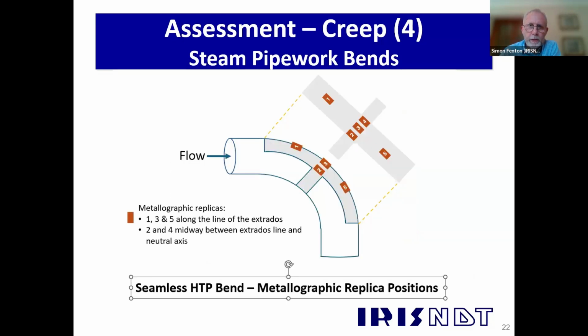Okay, next slide, please. So this shows the typical replication pattern for a bend on a main steam pipe or a hot reheat pipe. So we have 5 replicas there. We've got positions 1, 3, and 5 along the centre line of the extrados of the bend. And we go either side of that with replicas 2 and 4, just offset from the extrados centre line.